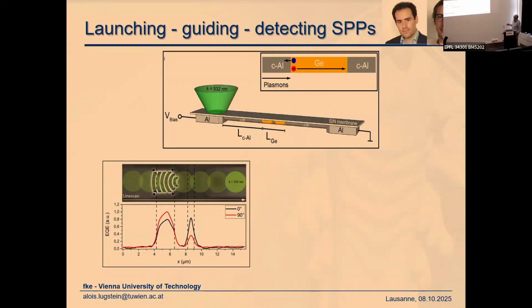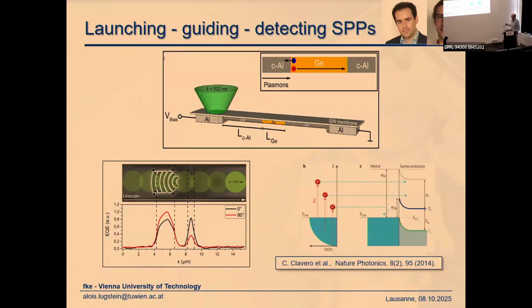So this peak, when we are at the top of the germanium segment, is just photocurrent. The light excites electron-hole pairs, and these can be detected. But we get an additional current peak when we are at the top of this grating. What we suppose happens is that we launch plasmons. The plasmons propagate at this interface, and at this interface these plasmons decay into hot electrons. Those with an energy higher than the Schottky barrier can make it over this barrier, traverse through the germanium segment, and can be detected as either plasmon-induced or photon-induced current.